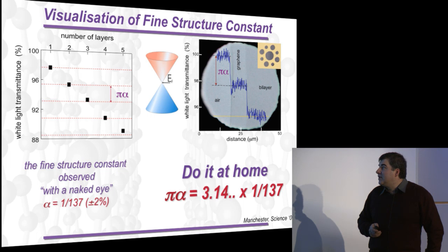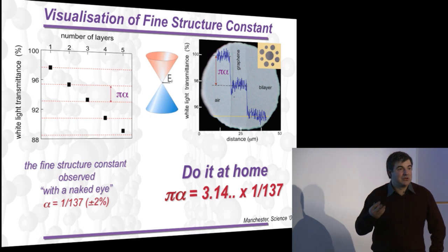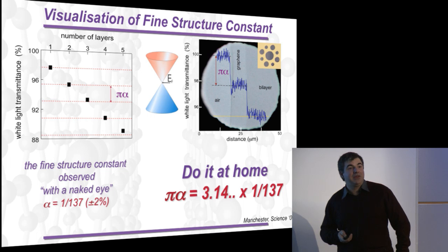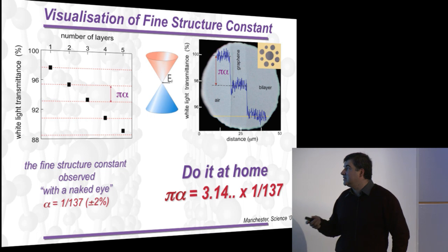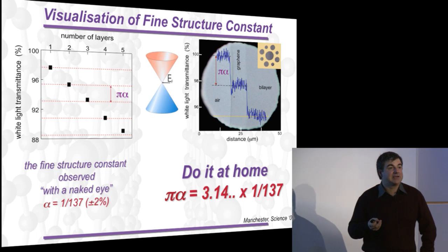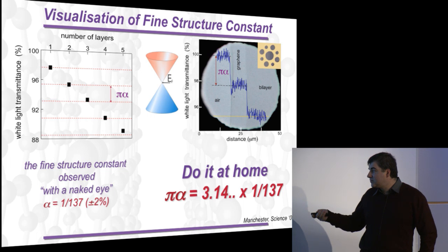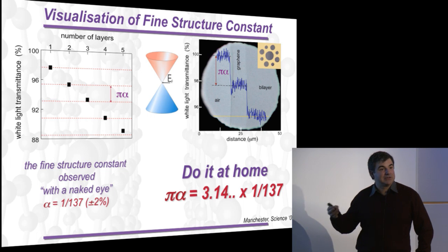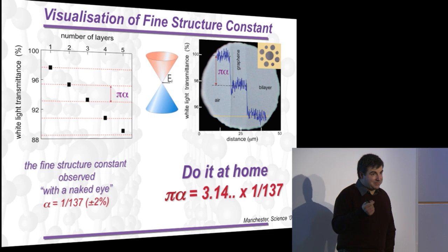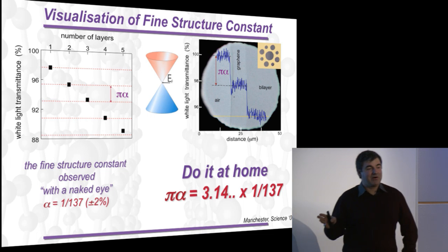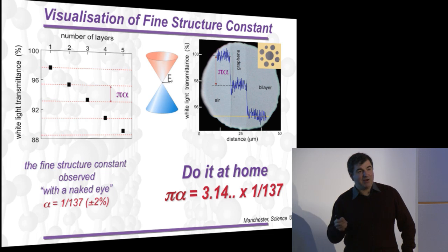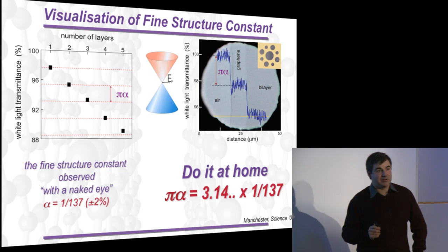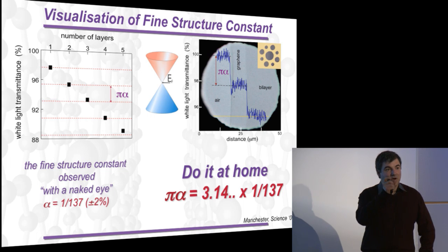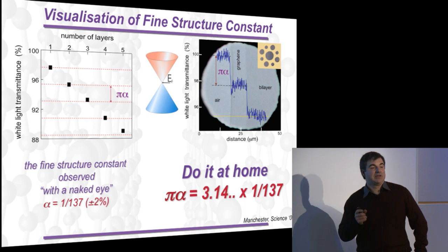Even more interestingly, this 2.3% is not just a number. It's actually given by a combination of the most fundamental constants. It's pi times alpha, where alpha is the fine structure constant. So do it at home: 3.14 divided by 137, you get 2.3%. And it doesn't depend on any material parameter. Wherever in the world you prepare graphene, it always absorbs the same amount of light. So you pick up a piece of graphene, look through it, and the contrast which you see gives you the most fundamental constant of this universe.